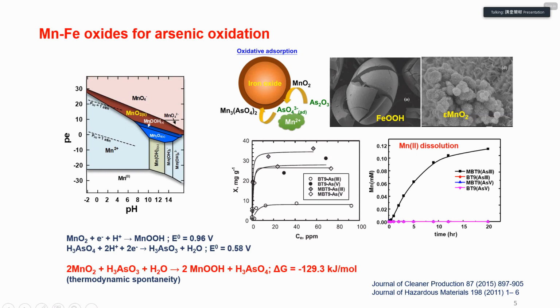And we can see this bimetal can significantly improve the total capacity. But the point is, in this case, the composite acts like the oxidant, rather than the catalyst. So most of the MnO2 is dissolved after long-term operation.